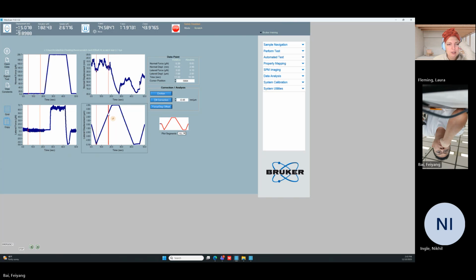It's pretty obvious here that we're tracing. We're at this normal displacement of around 0. We then load into the sample during this segment. And so we can see our normal force is increasing. Our lateral force is still at 0.